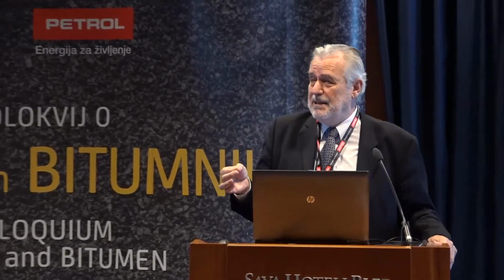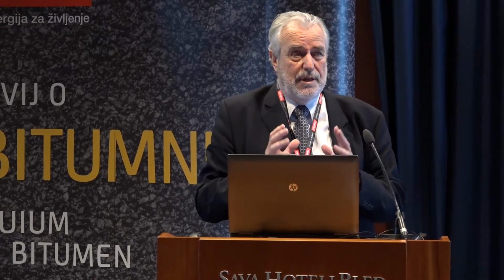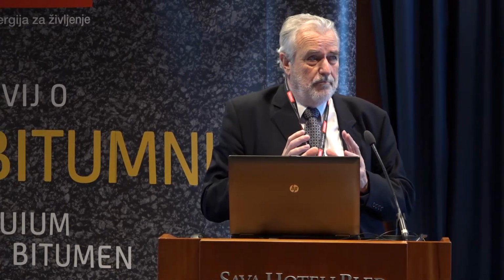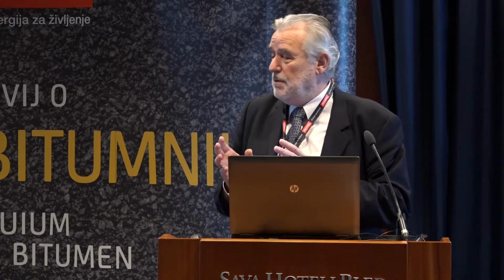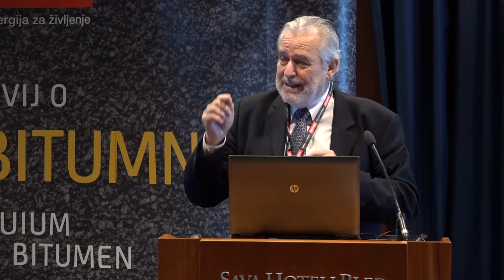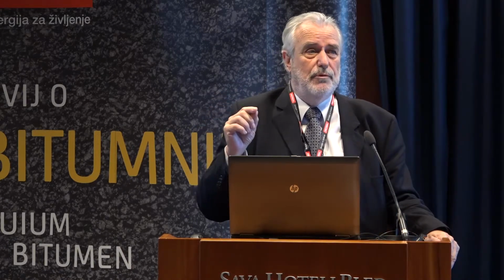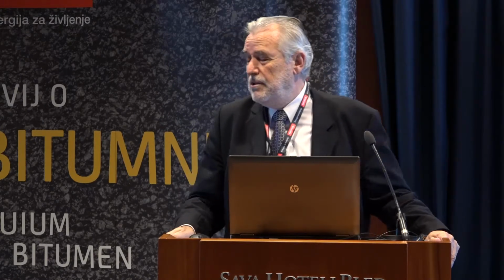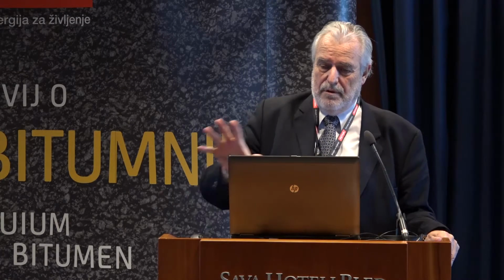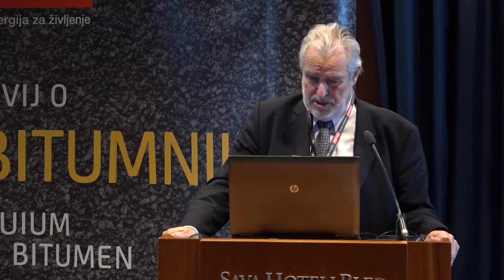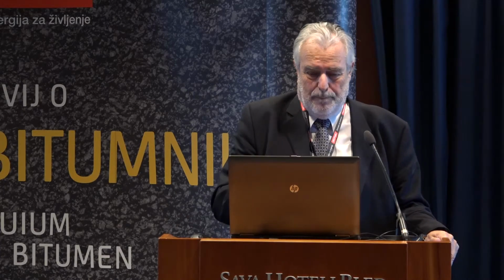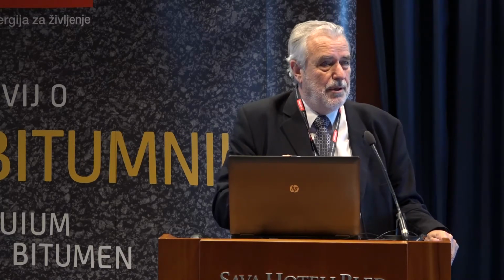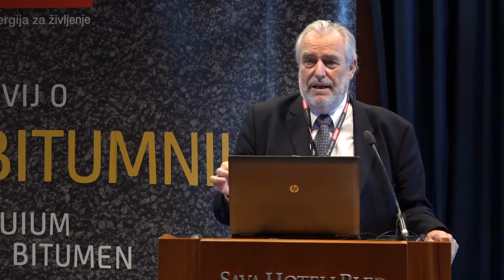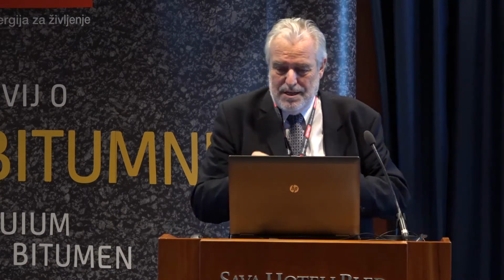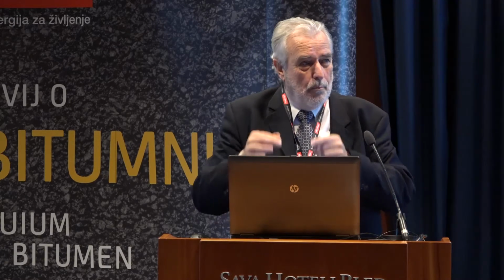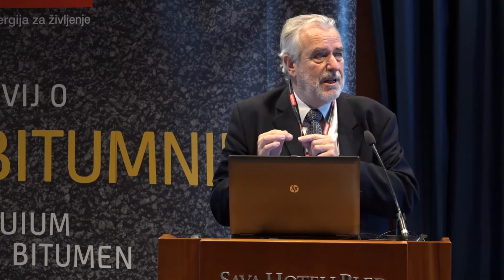Now, what does this mean in practice? We have demonstrated that you can build thinner layers, thinner roads. Obviously, the material that you are using, the highly modified binder, is more expensive. But at 20% reduction, that is already the break-even point. Now, we've made some model calculation using the Shell pavement design method, where we used different moduli for the sub-bases and the subgrades. And as you can see, the reduction in thickness varies between 29% and 58%. That means that these improvements can be made, and then you are above the break-even point.